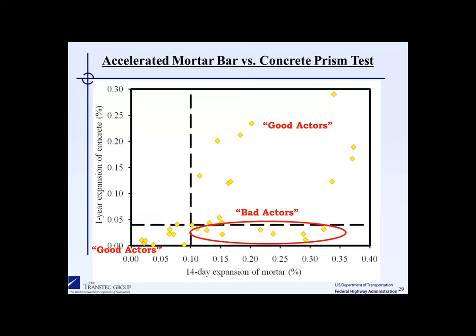We've done some work over the years to try to classify these aggregates. This is a bit of a joke here, but the aggregates that we consider to be good actors are those, and this is a follow-up to the last slide, where there's an agreement between the 14-day mortar bar results and the one-year concrete prism data. The data shown in this bottom left quadrant and the upper right-hand quadrant are considered to be good actors. These are aggregates that give the same answer in both tests, and this would be our most desirable situation.